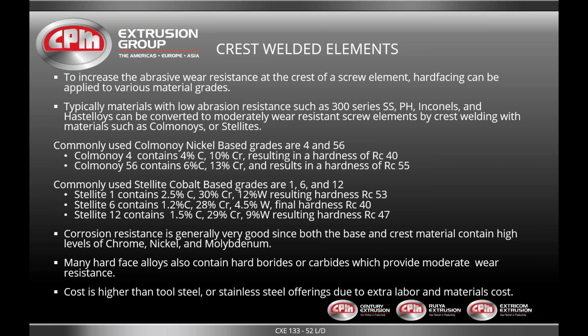The Colemannoys are a nickel-based product containing from 4 to 6% chrome... carbon, 10 to 13% chrome, and they'll result in a hardness of somewhere between 40 and 55, depending on which one we're using. The common Stellite elements are 1, 6, and 12, and they're a cobalt base. They contain from 1.2 to 2.5% carbon and 28 to 30% chrome, and contain tungsten from 4.5 to 12%, achieving a hardness of 40 to 53 Rockwell C.